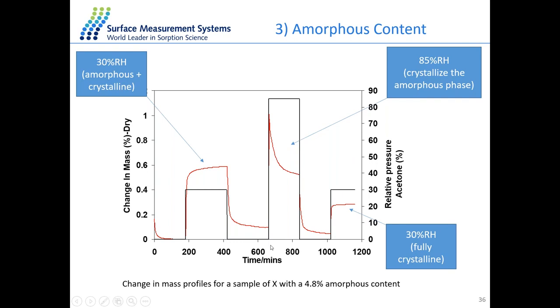And then what we do is ramp up the relative humidity to about 85% RH. So we know from our previous experiment that we obtain crystallization at around 60% relative humidity. So it's safe to say this has now undergone crystallization in this area here. Then we drop back to a stage again of 30%. So we now know that we are in the fully crystalline region of the sample. So we have the amorphous, the induced crystallization, and the crystallization stage. And the difference between these two is our difference in amorphous content.